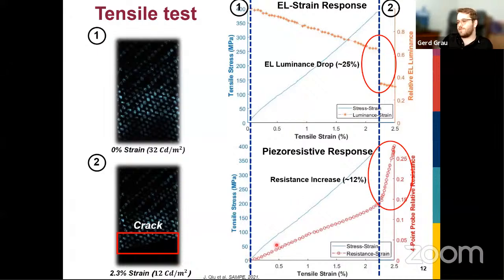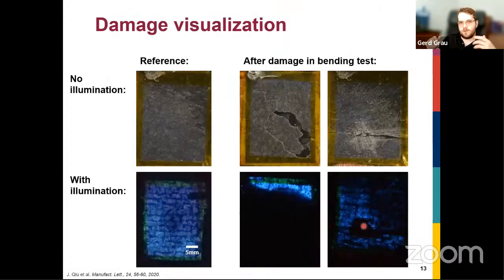And so this decrease in illumination happens because the resistance increases as we strain our carbon fiber composite. So you can do this in a uniaxial tension test. You can do other tests. We've done puncture, but also we've done bending tests. So here, for example, when we applied a large force, the whole sample basically cracked, and you can see all the light is off except here in the corner close to the contact.